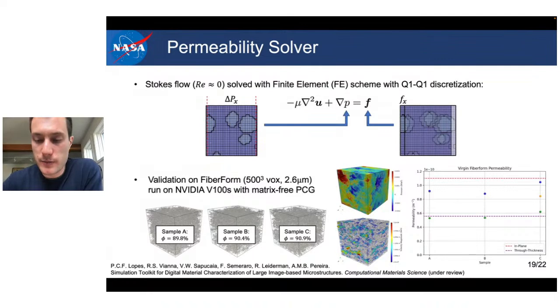And so the results on Fiberform look as follows, where the horizontal values are the in-plane and through thickness. Actually, Fiberform has a preferential alignment of the fibers. So that's why we call them the in-plane direction, and the through thickness is different because of this alignment of the fibers. And we can see that the numerical values that we obtained align with the trend of this through thickness and in-plane components pretty well.